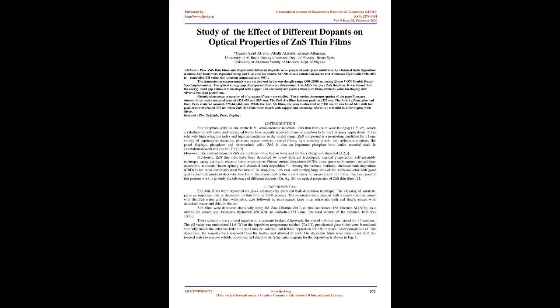The solution temperature is 70 °C. The transmission measurements were carried out in the wavelength range 300–2000 nm using Jasco V-570 Double Beam Spectrophotometer. The optical energy gap of prepared films were determined. It is 3.8 eV for pure ZnS thin film.